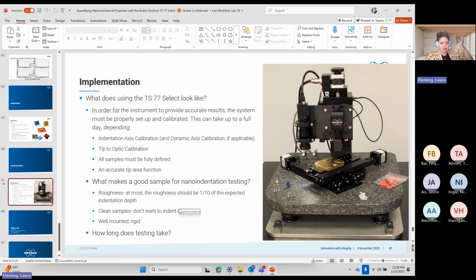And then the question is, what makes a good sample for nanoindentation testing? Roughness. We need to indent 10 times beyond the sample roughness in order to get accurate results. That means that you can test a rough sample, but you have to make sure that you're going deep enough to get beyond that roughness. It is nanoindentation, so the less rough a sample, the better.